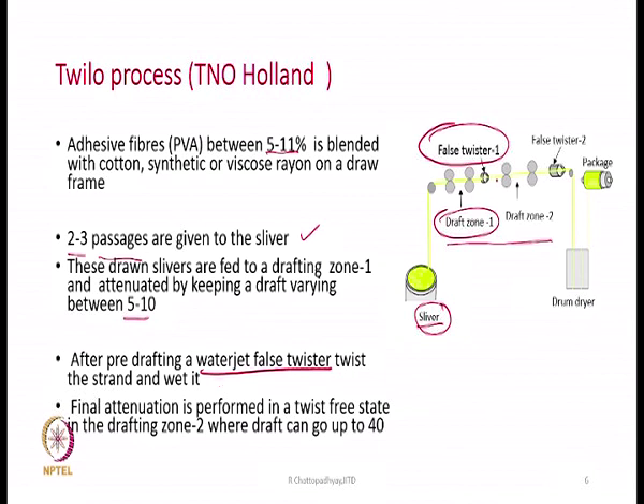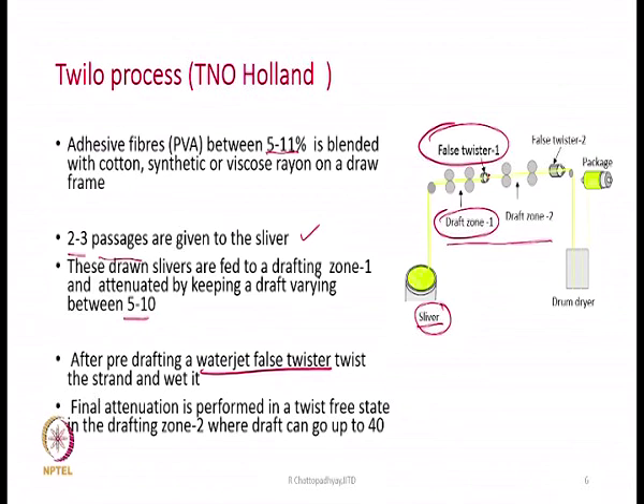And once it moves out of the false twister, to the right hand side of the false twister, there will be no twist left there. So, twist will be present behind the false twister, but there will be no twist present in front of the false twister, because we know that false twisting basically means that the S and Z twist cancel each other, which I have told many times, and therefore, in front of the false twister there is no twist left. It is again basically a bundle of fibers with PVA fibers dispersed within them, and the PVA fibers have already dissolved a bit and they have become tacky.